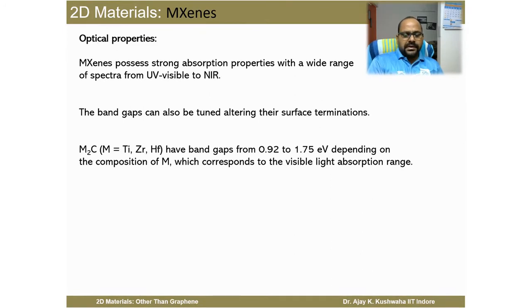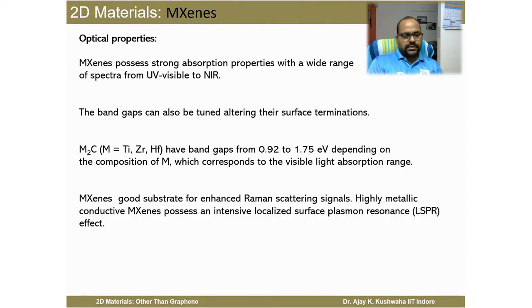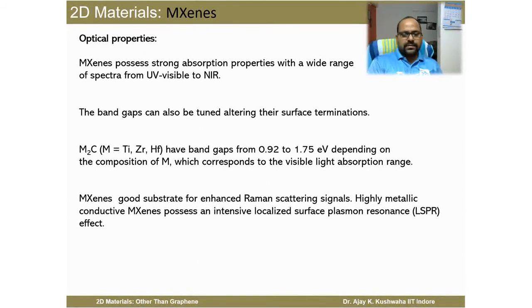For M₂C where M is Ti or Zr, the band gap was reported in the range of 0.92 to 1.75 electron volts. MXenes also show very good Raman scattering signals. This material can therefore be used for plasmonic resonance or localized surface plasmon resonance behaviors, enabling various sensing devices and other applications.